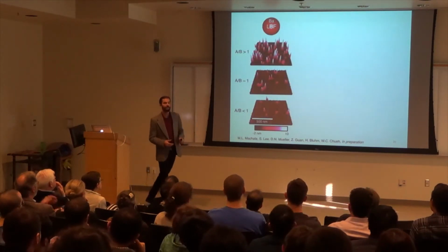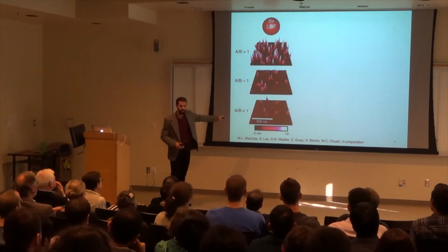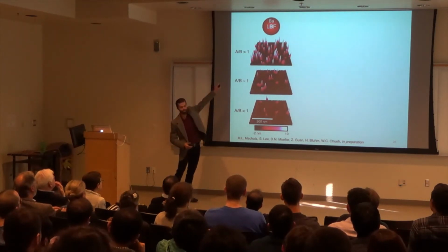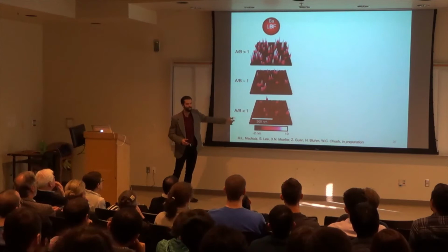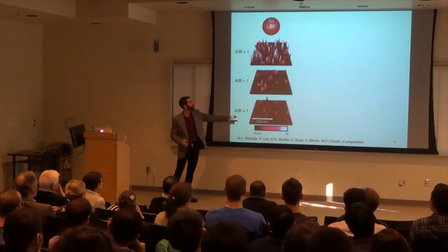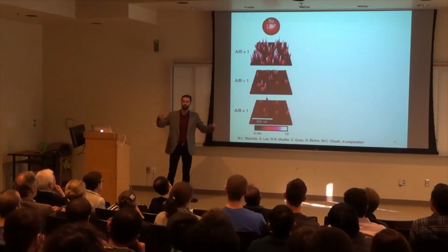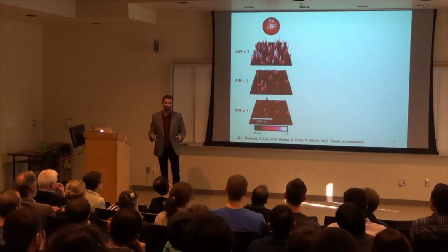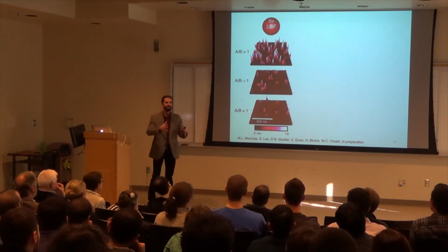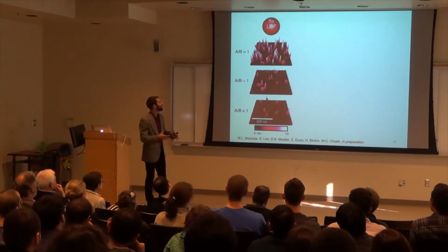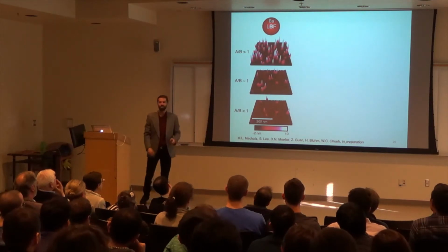So here's the barium sample. We have A site deficient on the bottom, moving up to A site excess on the top. And what you can see very distinctly is that you get these precipitates forming as you try to put more A site in there, which kind of makes sense. Barium is large, and we put more of it in there than the lattice can handle. And so it's precipitating new phases on top.